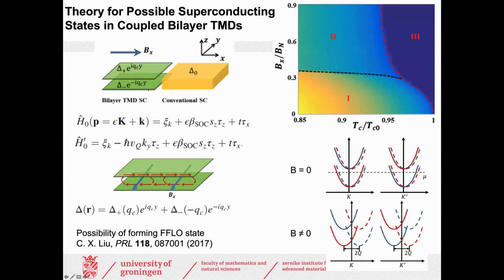Each of them is with a different phase factor. And this is not important because in normal conditions, if you have spin texture, they are cancelled with each other. But this is not the case once you apply a B field, in-plane B field, and these two superconducting states start to be coupled. So if you go to the Hamiltonian, we have the spin indice and the layer indice, and the layer is coupled by this T, this hopping term there.